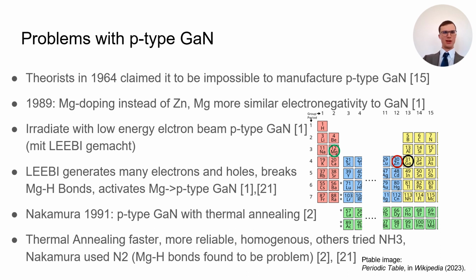However, the paper that talked about that was written way before Akasaki and Amano were able to develop the high-quality gallium nitride crystals that I talked about on the previous slide. And so Akasaki and Amano tried anew to dope with zinc, which had been the current p-type doping method for gallium nitride. However, this did not work, so they tried again with magnesium, which had more similar electronegativity to gallium nitride. Unfortunately, this also did not work.